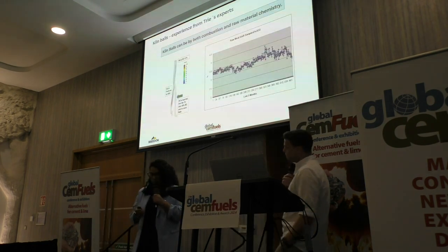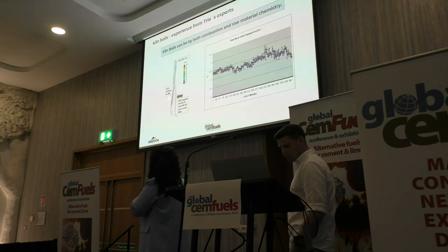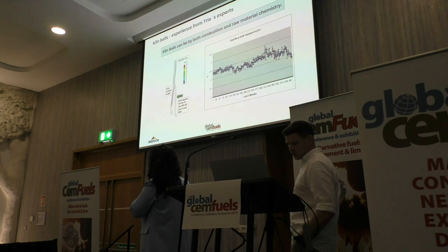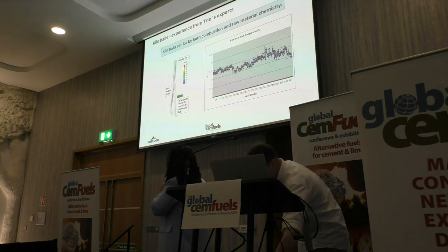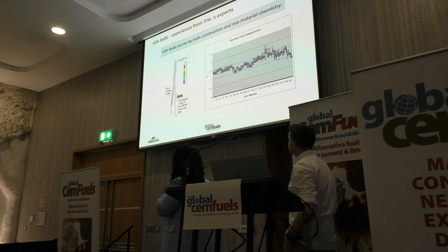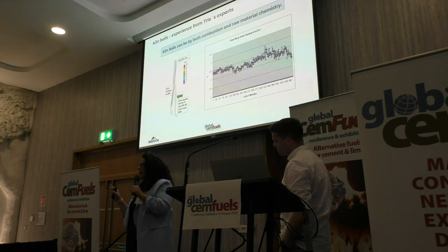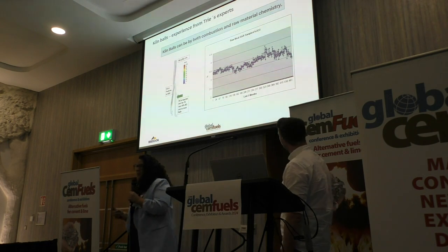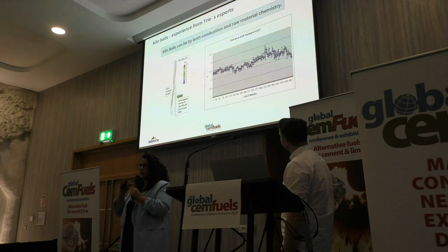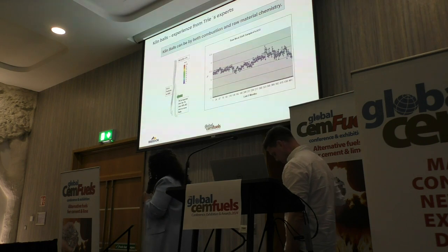They contacted us, and just to show our experience, this is one example of a plant in Australia we helped. They were burning high-cal fuel at that position, and they could not achieve burnout. They could not burn the combustion material above 41% burnout. Then we helped them to relocate, and they could achieve 99%. And it was like that: oh, the kiln ball problem solved, everybody's happy. And then 6 months later, I received a call: Oh, Joana, the kiln balls are back. We checked it. The fuel was still burning 100%, no combustion problem, but it seemed that it did not solve the problem. Then we checked again, and we found it was much more chemistry related at that time.